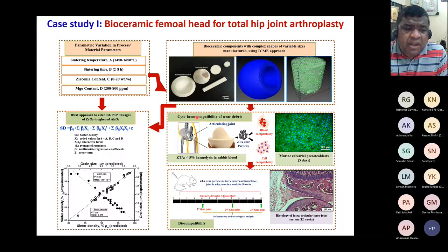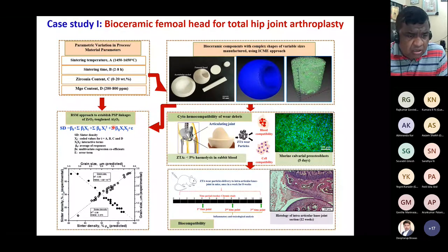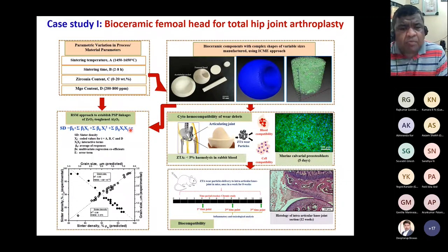which allows us to predict the sinter density and grain size at any intermediate processing conditions. And the things that we have varied are the sintering temperature and sintering time on one hand, and the material variables, which are the zirconia content and magnesium oxide content. And we use response surface modeling approaches, which solve multivariate problems where the coded values for A, B, C, D are fed as inputs on the right-hand side, and the interaction terms are also put as one of the terms on the right-hand side, and there is an error term, and then it allows us to predict the sinter density.